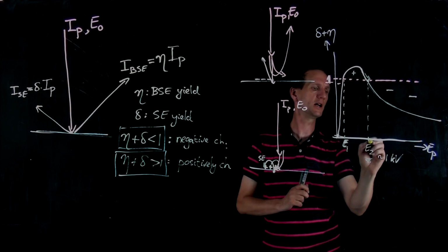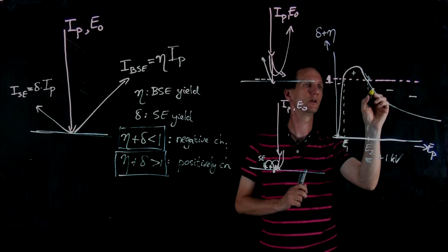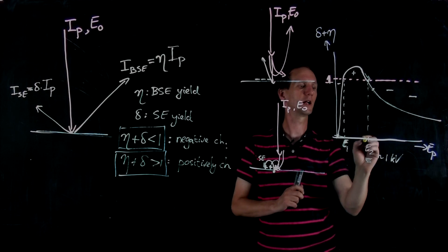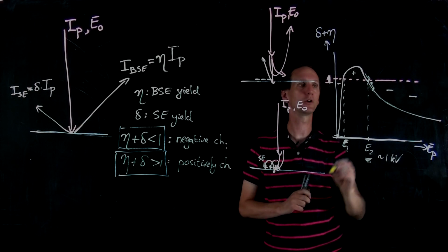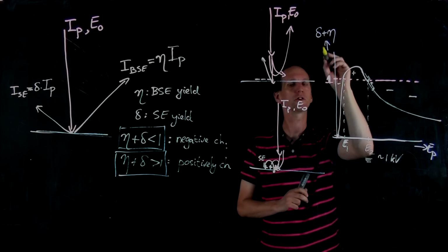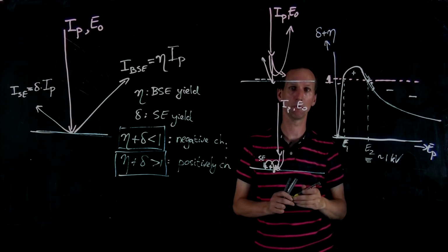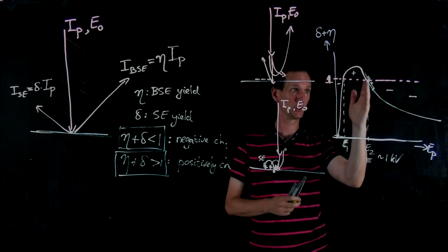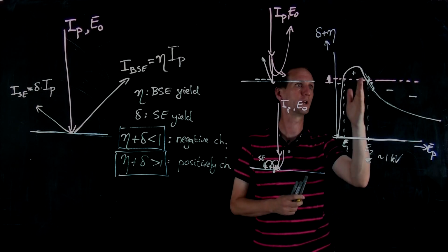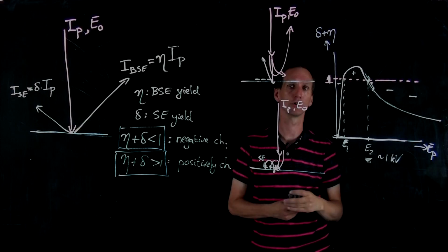Equivalently, if we are at slightly higher energies than E2, the sample may negatively charge. And in this case, the electron beam will be decelerated and we will gradually move up the curve, increasing the total electron yield until again we reach the point where we are at E2 and the sample will not show net charging anymore. Of course, this balance is very subtle, but it gives you an idea of what may go on if we are very careful in imaging non-conductive samples.